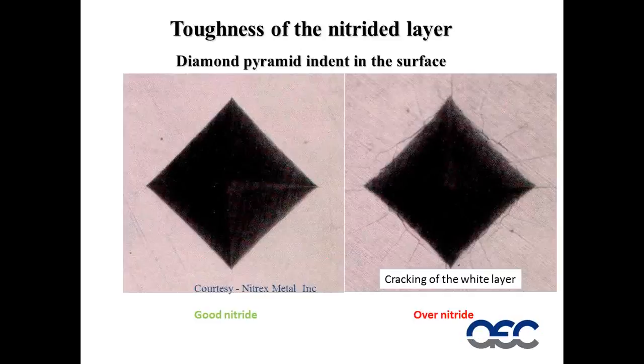If we take a close look at these little Vickers pyramid indenters that we put into a surface to look at the hardness of a surface. Here are two pictures courtesy of Nitrex, from one of Nitrex's publications. This left-hand picture is a pyramid indent which has been put into a good, hard piece of steel. You can see the pyramid is clearly defined and there is no cracking anywhere in the steel. On the right-hand side, you can see a surface which has been over-nitrided.